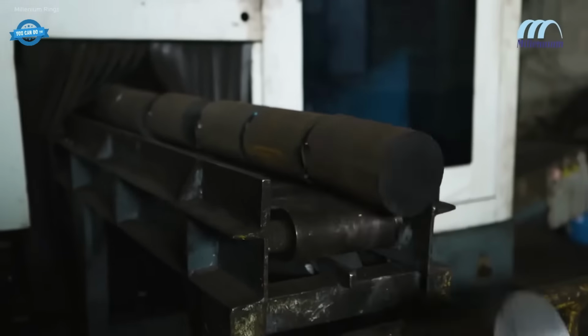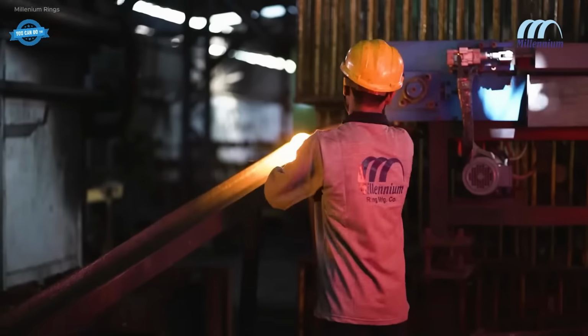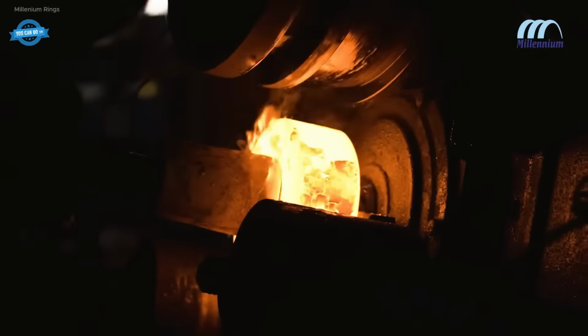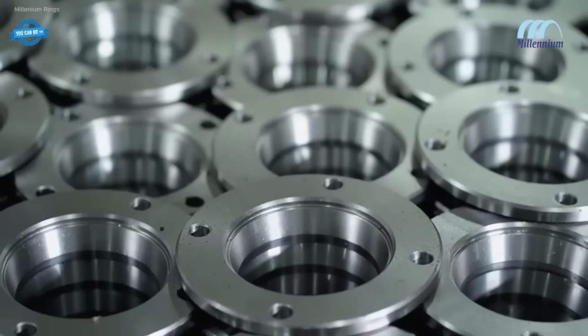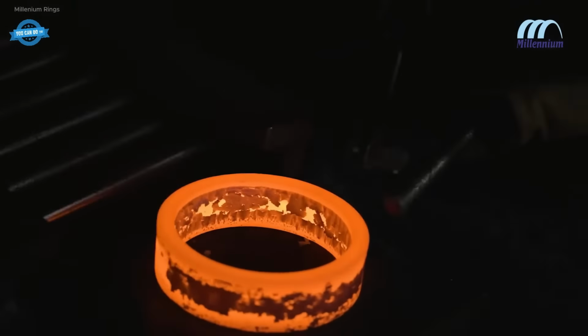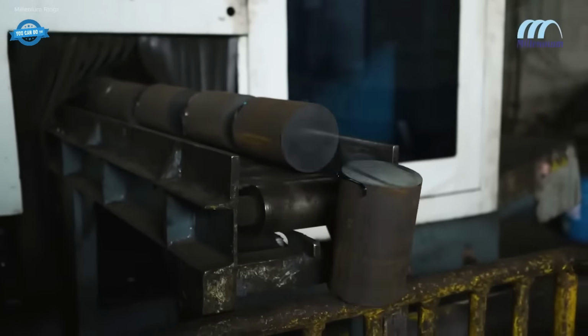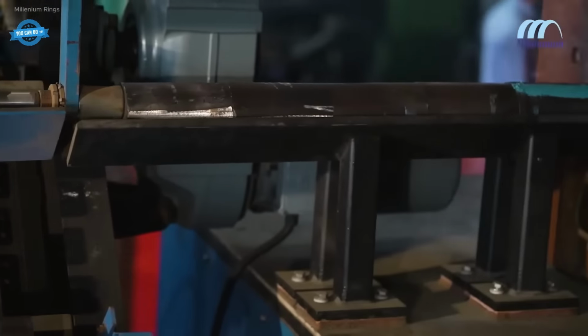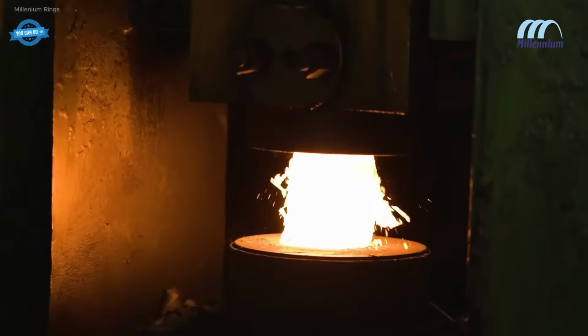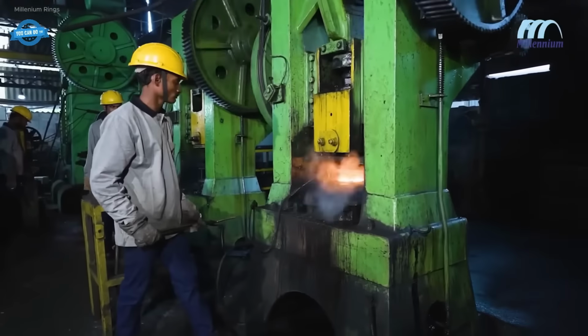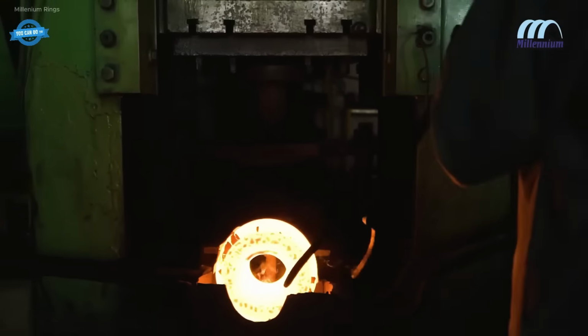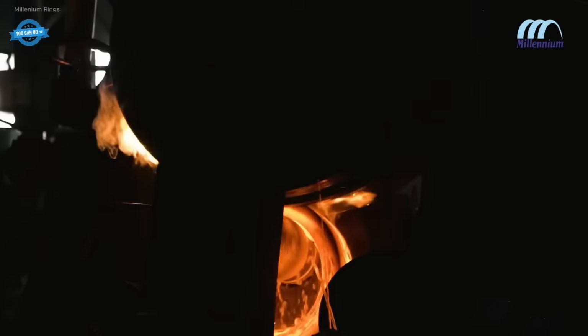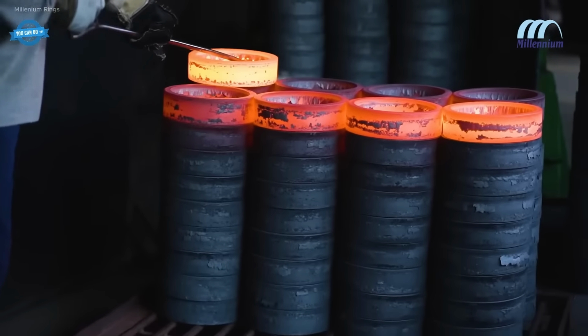Millennium Rings, established 2005 in Rajkot, operates 3 seamless ring production lines within a 72,000 square feet facility, delivering 20,000 TPY of forged rings. ISO 9001:2015 protocols govern every stage. Certified carbon, alloy, and stainless and non-ferrous billets are color-coded, sawn, then induction heated to forging temperature. MPM power hammers preform blanks, followed by a 3,000 kilonewtons radial-axial ring rolling press capable of sections up to 800 mm by 160 mm. In-house heat treatment furnaces perform normalizing, hardening, and oil-water quenching cycles to refine microstructure.